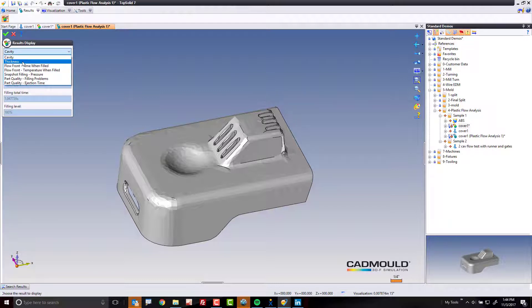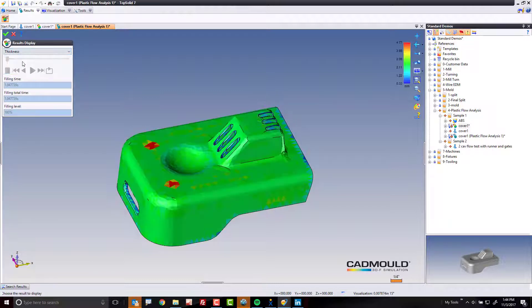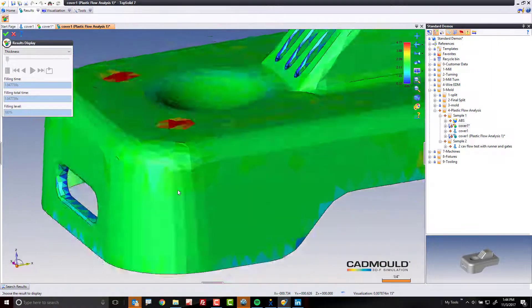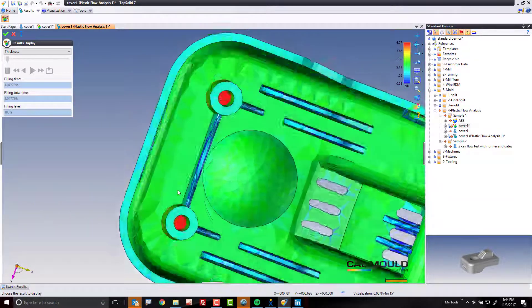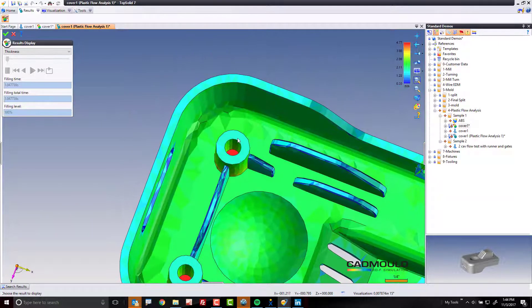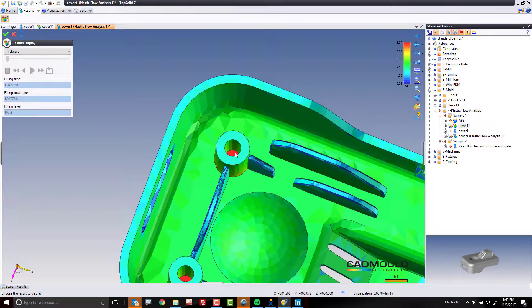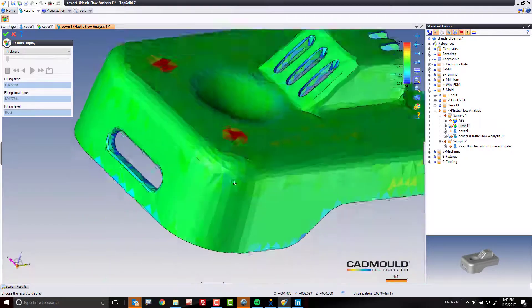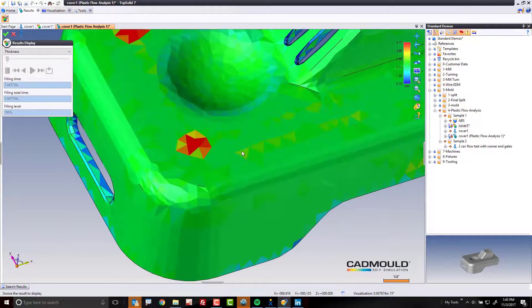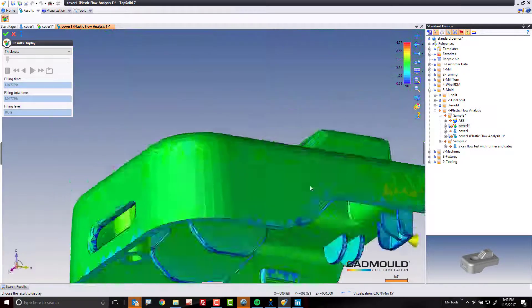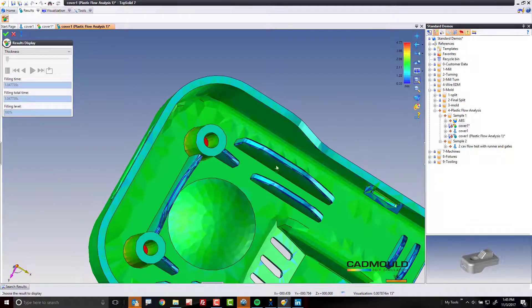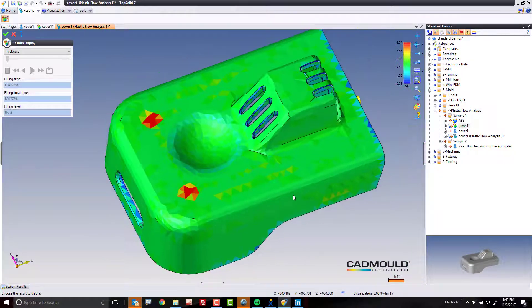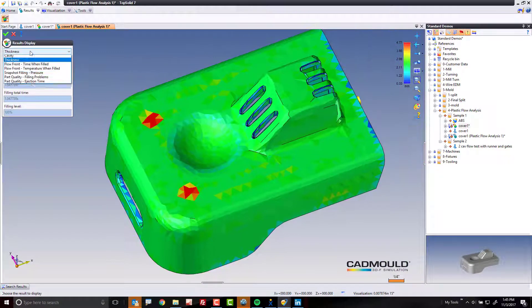Like that, I can go and check the thickness, for example. Here, I'm looking for any sink marks. Here you can see clearly there'd be some sink marks. If I flip this over, you can see why. Whoever designed this put a really thick boss type of rib here. And of course, that's going to cause a sink mark. Here you see a slight sink mark from the ribs. Not too bad. But the software is doing a good job of showing you that.